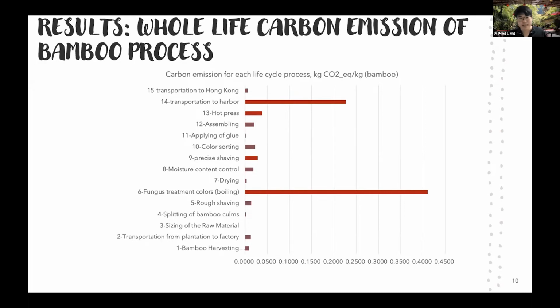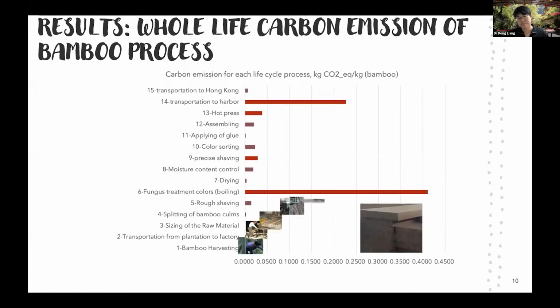So this figure highlights the process-based carbon emission for the bamboo products, and we can see some processes have the potential to be improved in future. For example, the much higher emission comes from, as we can imagine, the transportation, for example from the mainland to Hong Kong due to the shipment. Also some higher carbon emission is accounted for by the fungal treatment, and processes like shaving and the hot press. They use steam and have very high internal energy consumption.